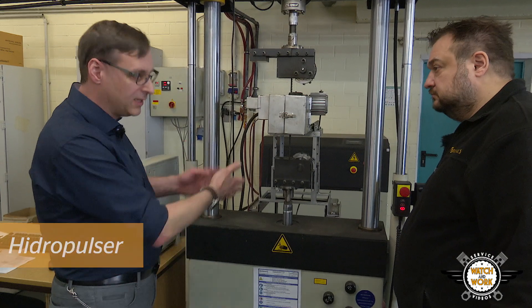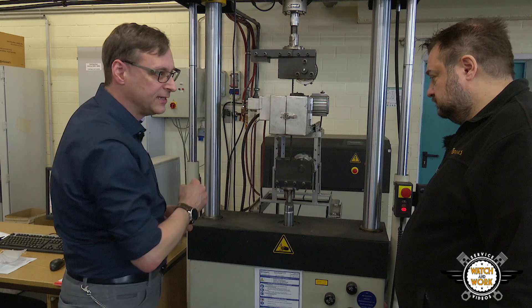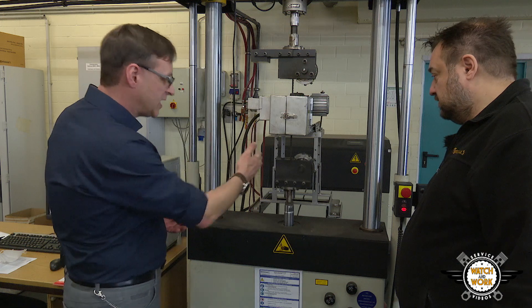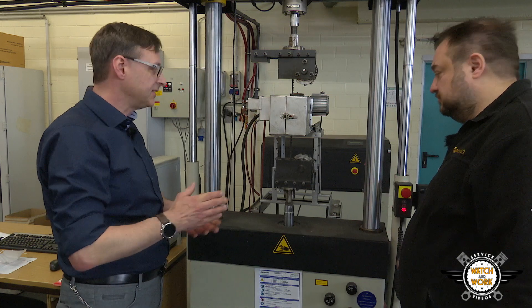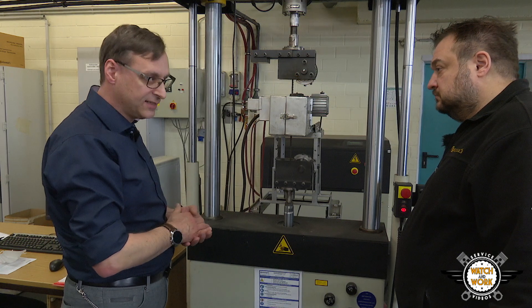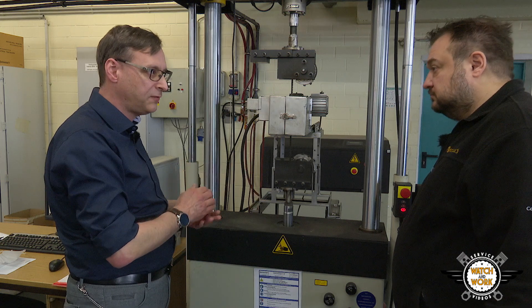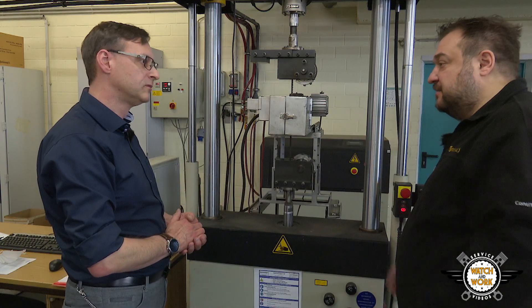This is our hydropulse shock testing machine. In the middle we have a heat chamber at 150 degrees and a timing belt that has been cut open. Every time there is an impulse from the fuel injection pump, the timing belt is deflected due to the pump's high load. This is reproduced 20 times a second in this fatigue test. We manage around 1.7 million impulses a day, but the belt will have to endure over 700 million during its lifetime. So we test under overload conditions with increased forces and then work out the belt lifetime at lower forces — meaning the belts have a built-in safety margin again.